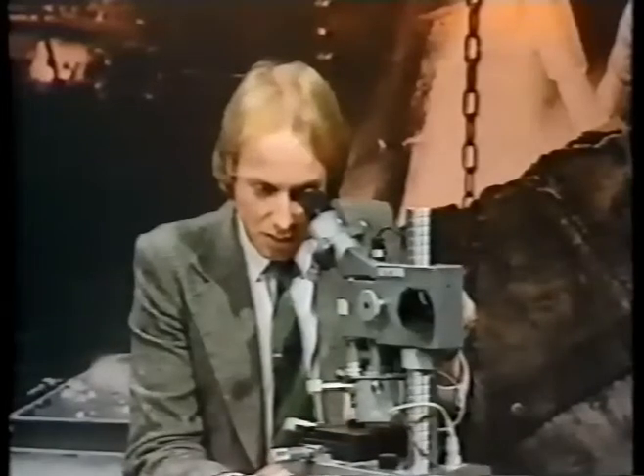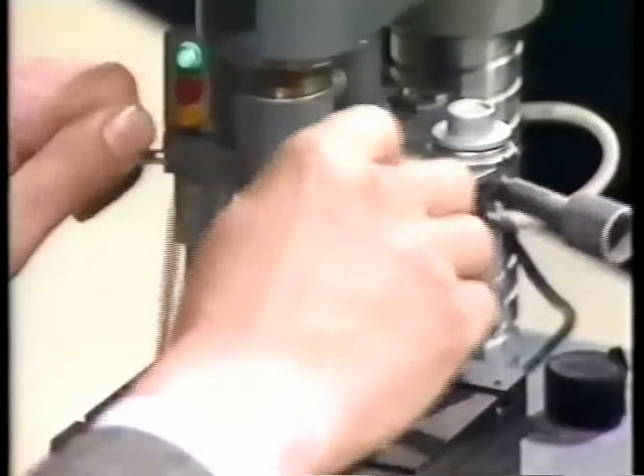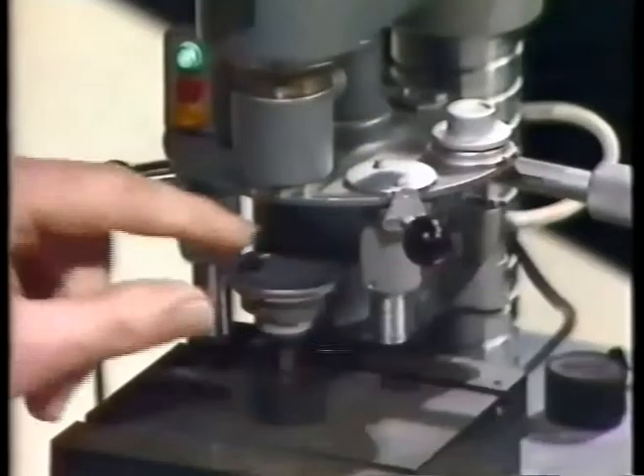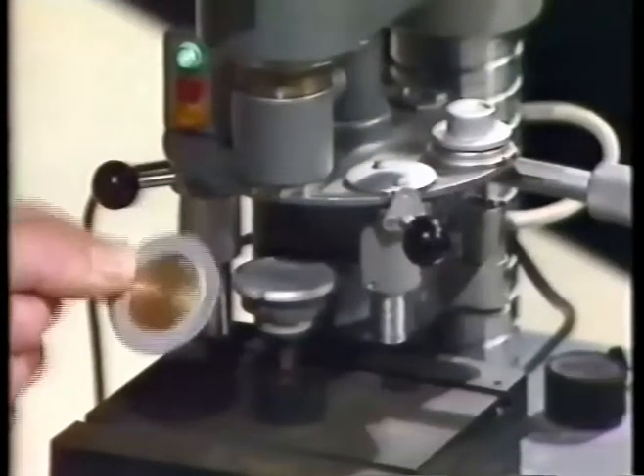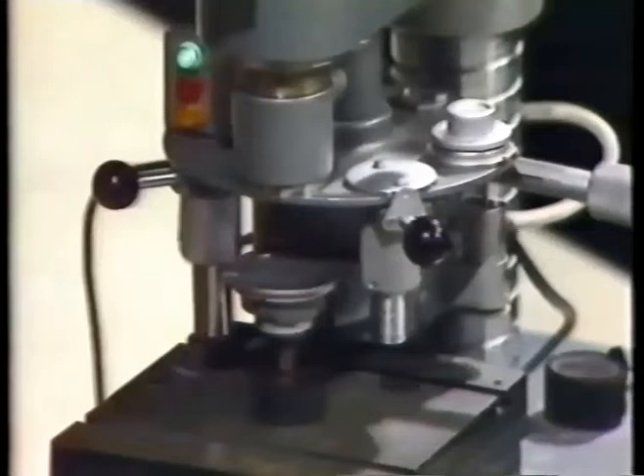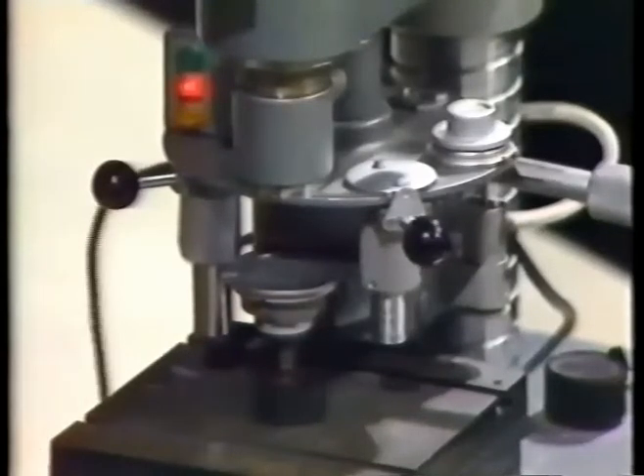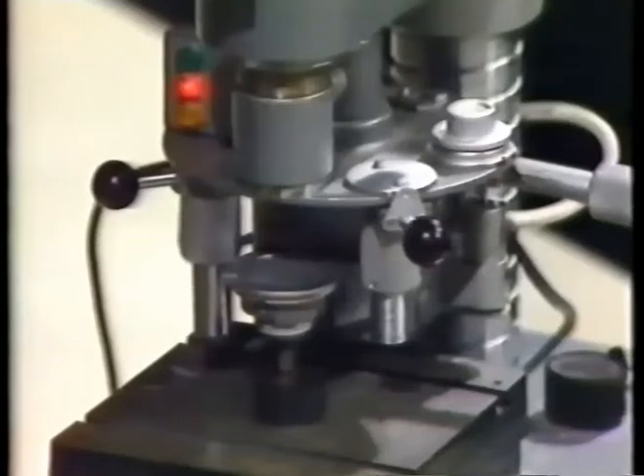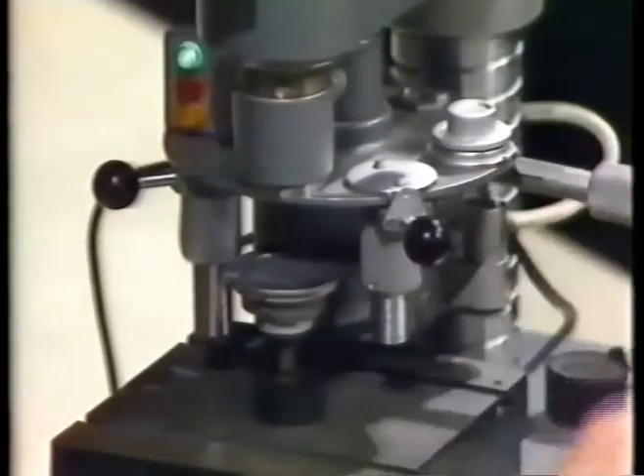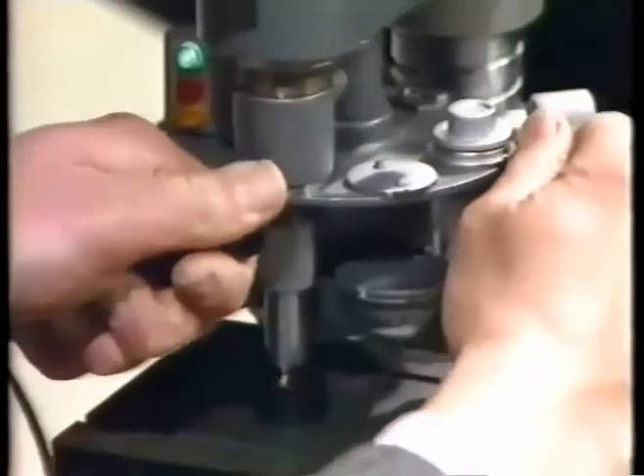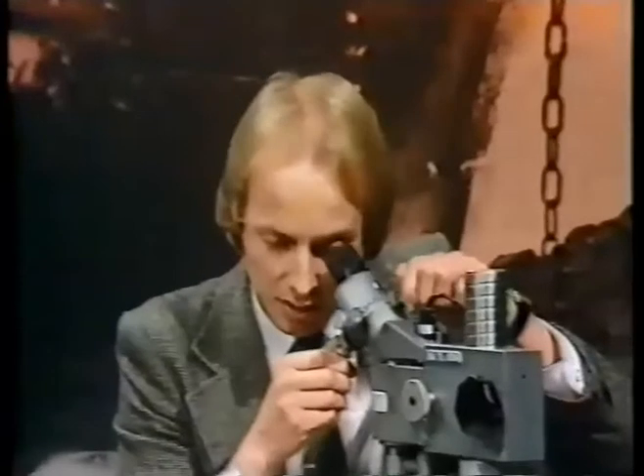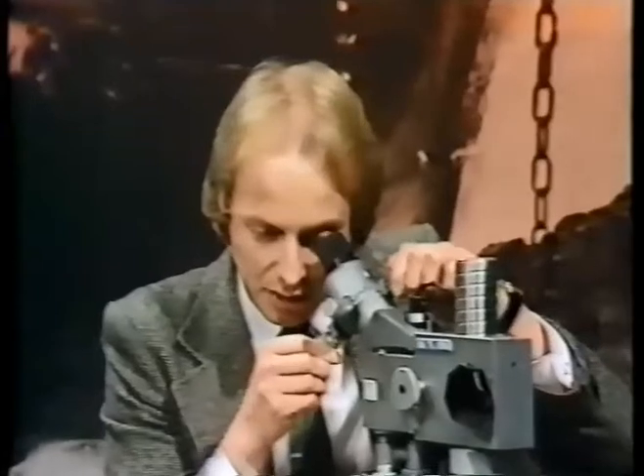focus, and then bring round the diamond stylus, and I've chosen a small load to apply to the stylus. I then trigger the loading sequence, and the red light tells me that it's begun. The orange light tells me the sequence has been completed, and I can now withdraw the stylus and measure the size of the indentation left.